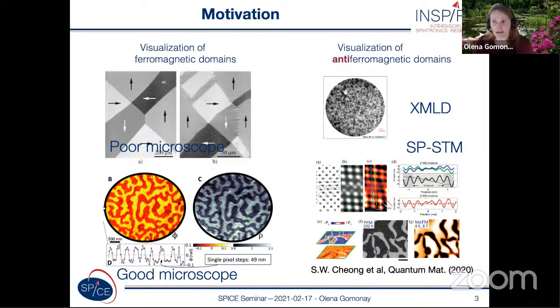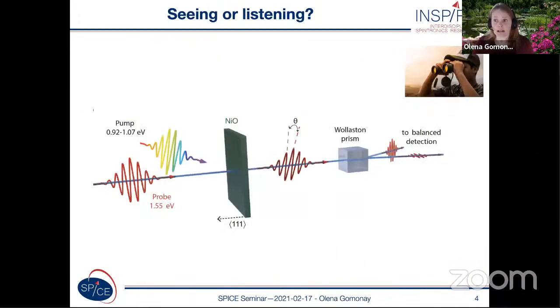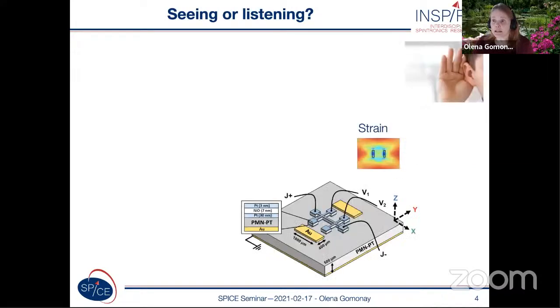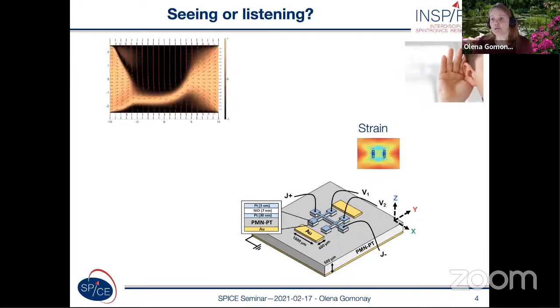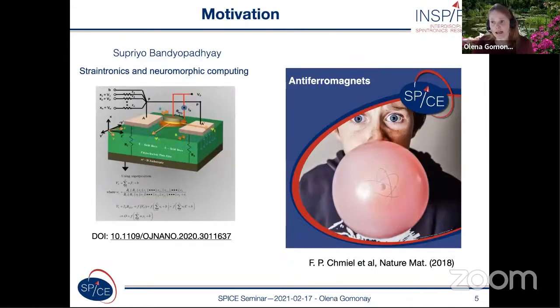However, antiferromagnets show a quite pronounced magnetoelastic coupling between spin and lattice. And we can use this. Instead of looking at antiferromagnets by light or X-rays, we can try to listen to them. We can try to apply strain or stress to look at the strain response and then reconstruct the magnetic structure of the antiferromagnetic textures. On top of this, magnetoelastic effects could be very useful for applications, as we know, for example, from straintronics, which at the moment is well developed in application to ferromagnetic materials.